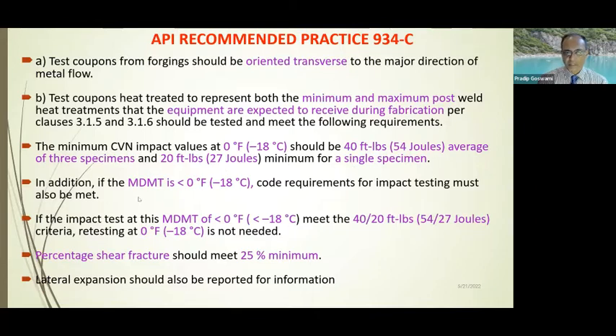That's the minimum requirement. And in addition, if the minimum design metal temperature is below minus 18 degrees centigrade, code requirements for impact testing is a must for the design code, and as mandated by your project specification. If the impact testing at this temperature meets these particular values, 54/27 joules, that is the average and the minimum, retesting at minus 18 degrees centigrade is not needed. Well, this is a very specific requirement that needs to be looked at when it arises. And percentage shear fracture should be 25%. Lateral expansion also should be reported in the material test report.